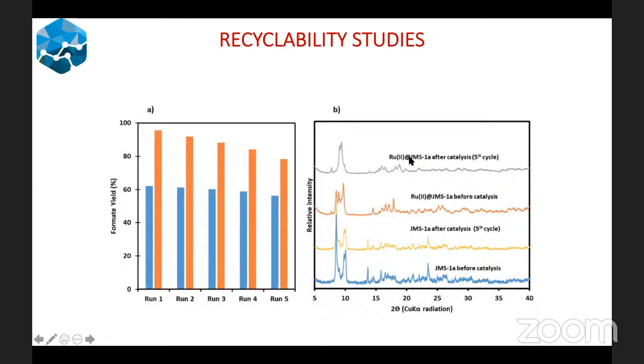And of course, with the ruthenium functionalized MOF, this is before the first cycle and after the 5th cycle, you can clearly see that you still have some peaks that are retained, which also confirms some degree of rigidity of our MOFs. It means that these catalysts are very good. But of course, you can see that they don't necessarily match, but there are some similarities between your catalyst before it is used for catalysis and after catalysis.